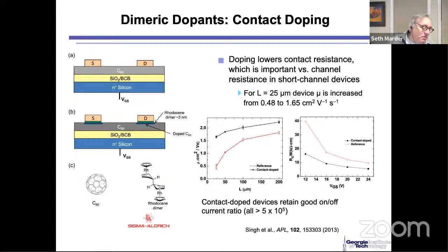So what you suggested is that there could have been an impact of doping on that contact resistance. Here, we ensured that there was a good level of doping, because we put enough material to pretty heavily dope and change the conductivity of the material between the electrode and the intrinsic C60. Does that clarify?